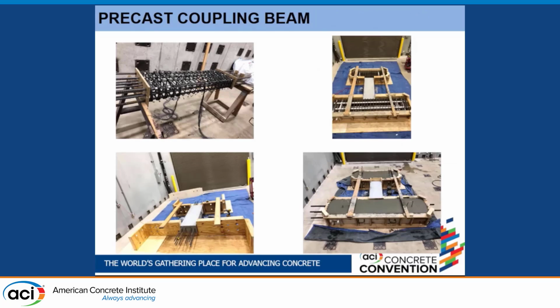Just mentioned that we prefabricated these, so we started with the reinforcement cage. Then we cast the fiber concrete for the coupling beam. Then we put it in place. We have 2 massive, very large stiff blocks simulating the edges of the walls, the wall being connected. Then we cast the regular concrete for the walls.